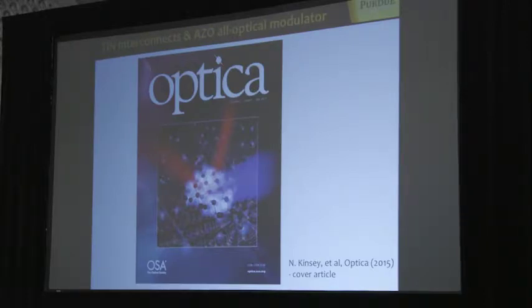Because they provide an absolutely unique opportunity to switch. If you work very close to the point where epsilon is near zero, it means that if you slightly increase epsilon, your material becomes dielectric. If you slightly decrease your epsilon, it becomes metallic. You basically switch from metal to dielectric, which is a dramatic change in terms of the optical properties. So the refractive index in this case could be changed by 100% easily. And you do it very easily because you're sitting close to the point where epsilon is near zero. And that's where all the wonderful properties come from.